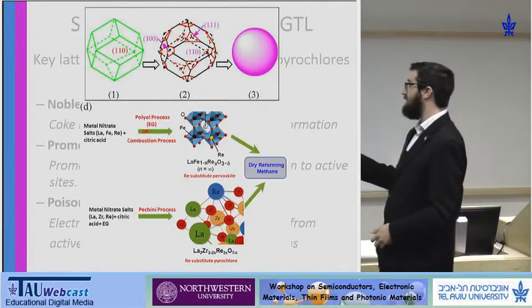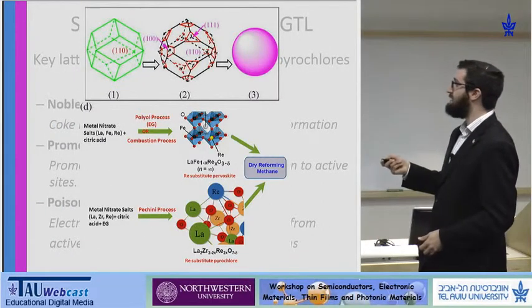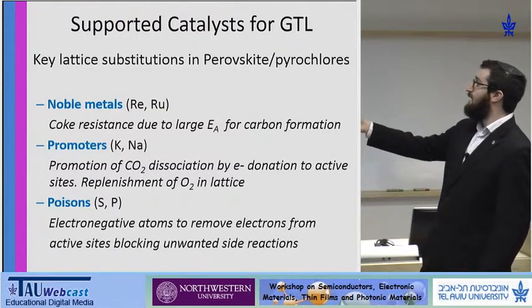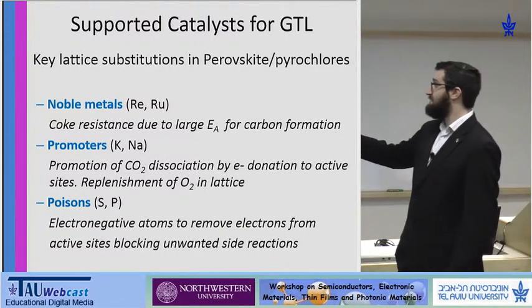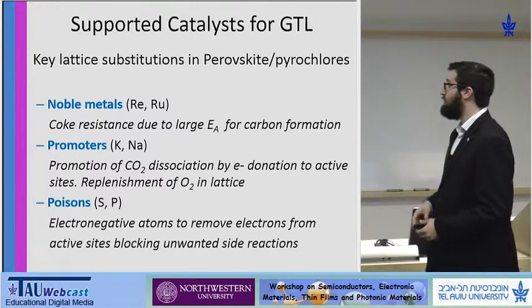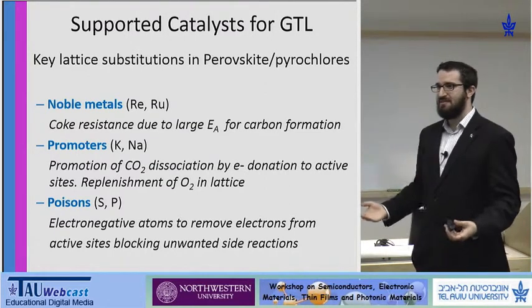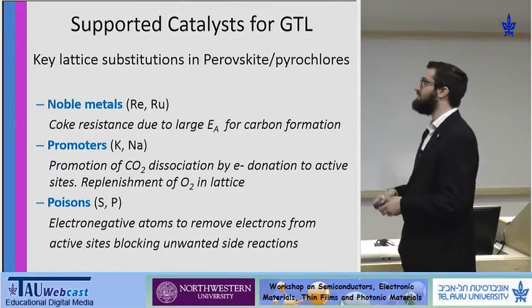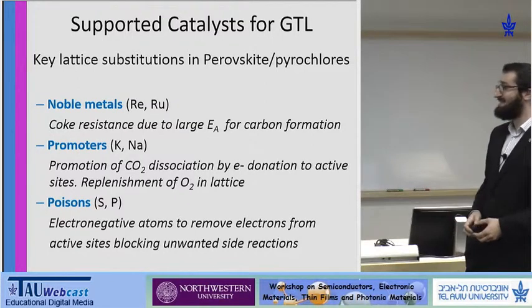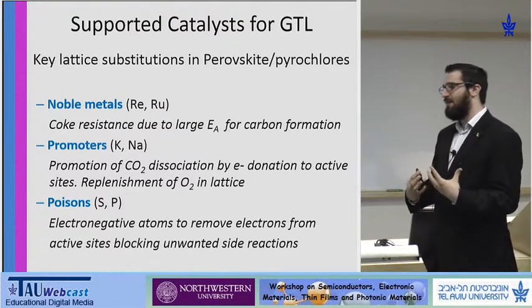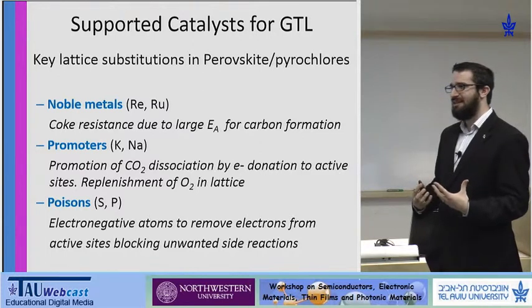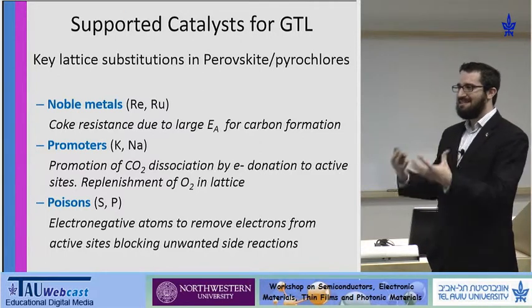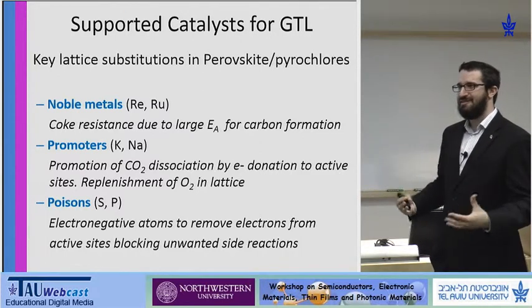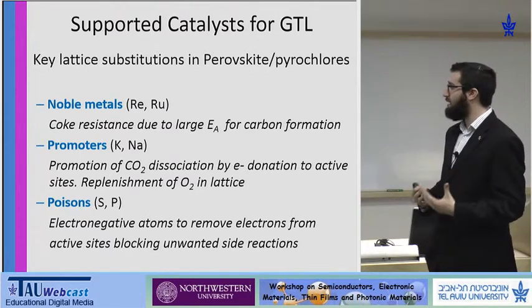I should mention that the substitution will also be rhenium, but the other types of substitutions can be promoters, for instance, potassium and sodium, which can donate electrons to active sites in order to decompose carbon dioxide more easily. The fact that a lot of perovskites have a high oxygen mobility could be a method to oxidize solid carbon off the surface and resist coking.